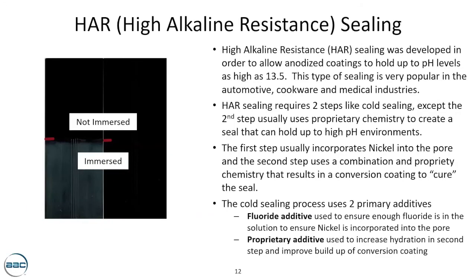All right. So the next slide here is high alkaline resistance. What this sealing process entails is usually a cold seal step on the front end, followed by a hydration step of some sort, or a second step seal on the back end, which can vary in terms of the type of chemistry used. But the critical portion of this is the type of cold seal chemistry you're using and how that cold seal is managed.